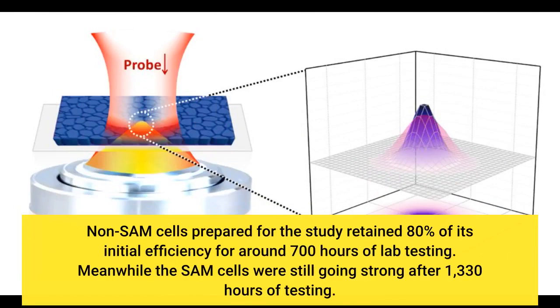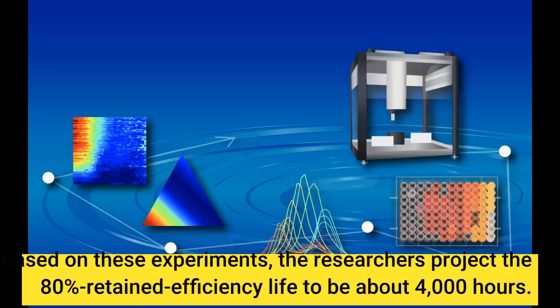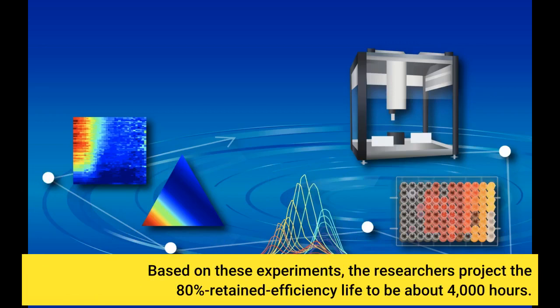Non-SAM cells prepared for the study retained 80% of their initial efficiency for around 700 hours of lab testing. Meanwhile, the SAM cells were still going strong after 1,330 hours of testing. Based on these experiments, the researchers project the 80% retained efficiency life to be about 4,000 hours.